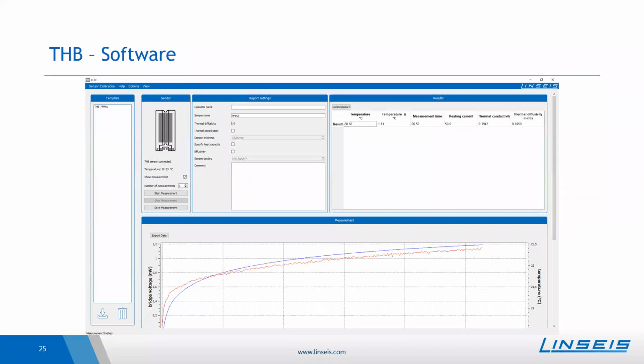So with the THB, it's only possible to determine specific heat capacity in the calorimeter function, where one determines the 3 thermal properties at the same time. So there's not a specific cell for the specific heat capacity independent measurement. To have the highest accurate specific heat capacity, I would recommend to use a DSC or a calorimeter in general, because here the system is then specified for the CP determination, whereas the THB is more focused on the thermal conductivity determination, but one has the advantage to also have a value for the specific heat capacity. It might be not the most accurate one, but one at least has an orientation with a rather low uncertainty.